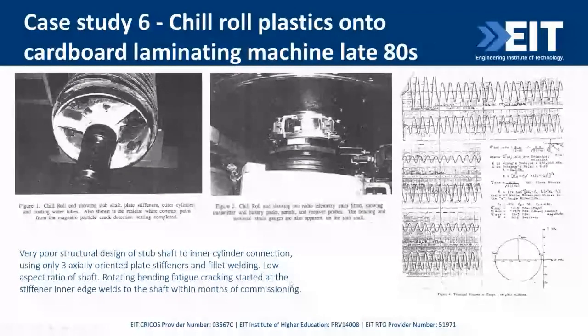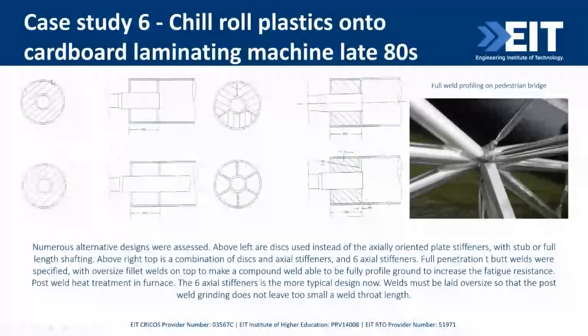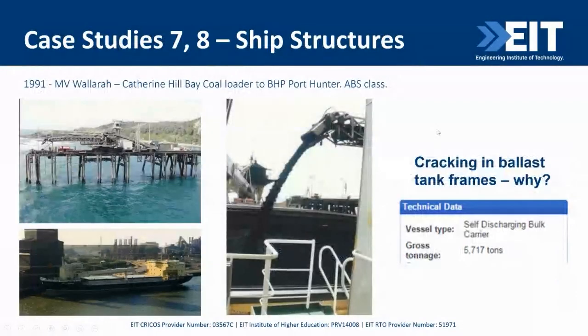So we sorted that out, obviously, with gauges and telemetry, and looked at different rectifications with discs and stub shafts, with discs and continuous stub shaft, higher ratio aspects, but they obviously would stop you getting access to your water hoses and connection coming in and out. And the best solution obviously was 6. So very basic, 6 gussets, increased thickness at inner and outer edges, full pen, oversized welds, fully profiled, similar to this joint, which is on a pedestrian bridge. So, this joint here is aesthetics as well as structural. But where needed, on a low production item like this, you can beneficially use full profiling on oversized welds and stress relief.